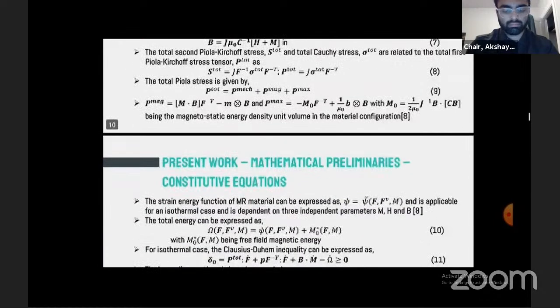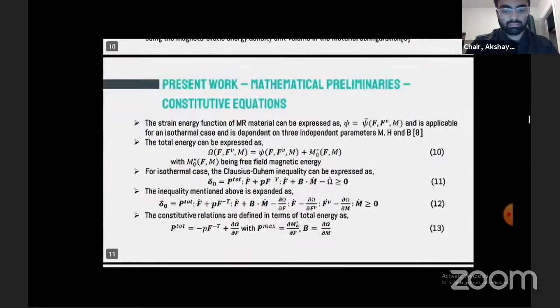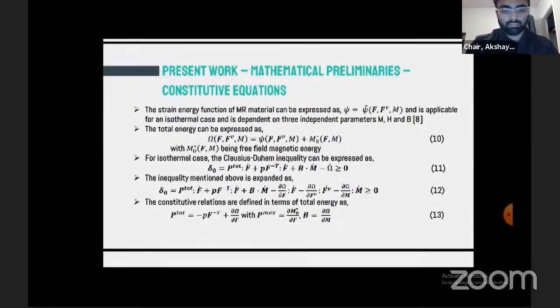The constitutive equations involved in the development of the model are as follows. The strain energy function of the material can generally be described as a function of the deformation gradient, internal variable, and the magnetic variable, and is applicable for all isothermal cases, depending on these three independent parameters. The total energy is expressed as shown in equation 10, with M0 being the free field magnetic energy. For an isothermal case, the Clausius-Duhem inequality can be expressed as shown, and is expanded as shown in equation 12. Using these, the constitutive relations are defined in terms of the total energy as shown in equation 13.